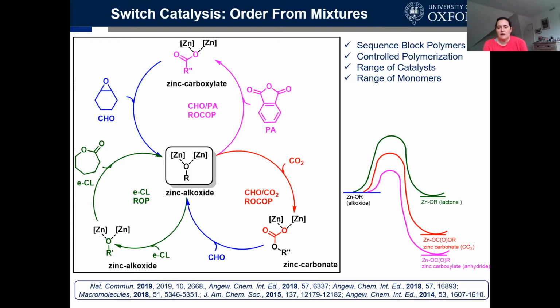So now I'm looking over at the right-hand side where you see the barrier height in those very rough sketches, trying to show you how you go from an alkoxide to a range of insertion products, and the stability of the linkage formed. We also see that carbon dioxide has quite a low barrier, but it forms a much less stable linkage, and so there's some possibility for reversibility in CO2 insertion chemistry. In contrast, lactones, caprolactone, tend to have higher barriers and the least stable linkages of all.